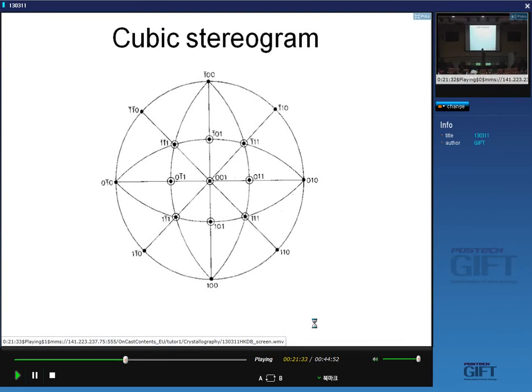What is the symmetry parallel to that edge? So what is the symmetry of the 0, 0, 1 cubic direction? Rotational symmetry? Fourfold, because at every 90 degrees you reproduce the cube, don't you? Yeah. So notice that we have fourfold symmetry about this axis here, here, here, and here. You have 0, 1, 1 type directions. Similarly, this is the 1, 1, 1 type plane, and you can see threefold symmetry there. If I now focus on this axis here, again, you can see fourfold symmetry because you have this, this, this, and the one going into the plane of the diagram.